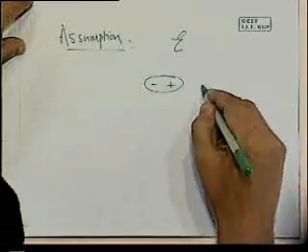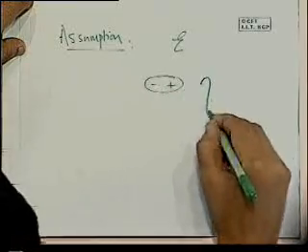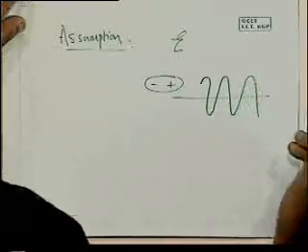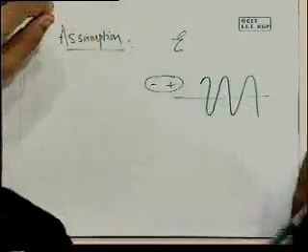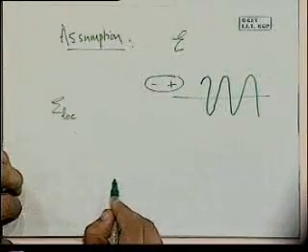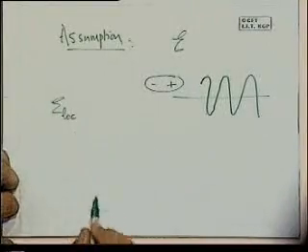So what we will see is that if you look at it, a periodic arrangement of dipoles, we go up and down around this average value, which is the applied field. So if you average it out, it comes out to be the applied field. But for various reasons, namely the individual dipole that is there is going to experience the dipoles around it, and so the local field is going to be rather different from the field that we are looking at, namely the applied field, which we had, the overall field. Okay, so once we have induced this dipole, we are going to have a change. And we are interested in knowing what is the local field that a particular dipole experiences.